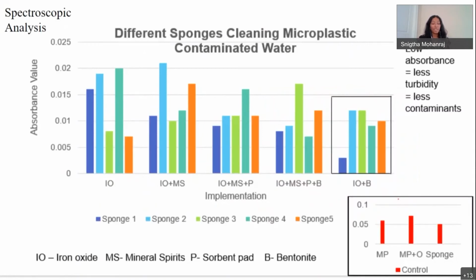So in the spectroscopic analysis, I used a laboratory spectrometer which measured the absorbance of different contaminated samples. So the lower the absorbance, the lower the turbidity, thus indicating that there are fewer contaminants present. And so I tested each of the 5 sponge types across each of the 5 implementations of iron oxide and the additives. And it was shown that iron oxide and bentonite was the best for cleaning microplastic contaminated samples.